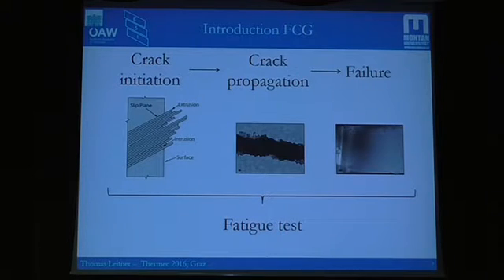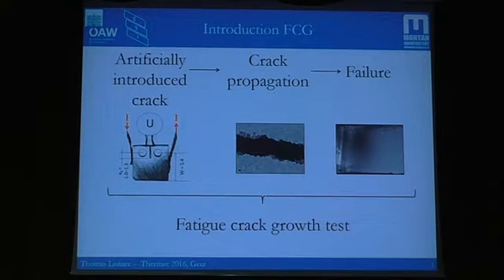So when we usually do fatigue tests, we start with quite perfect specimens and we cyclically load them, and what we measure are the number of cycles needed for crack initiation and crack propagation until failure. When we now take away this first step and artificially introduce cracks, we do fatigue crack growth tests and monitor the crack propagation until failure.